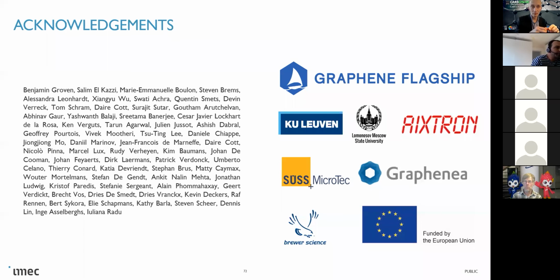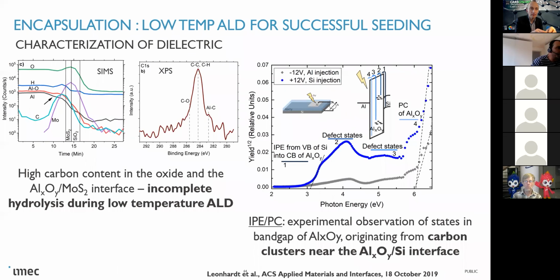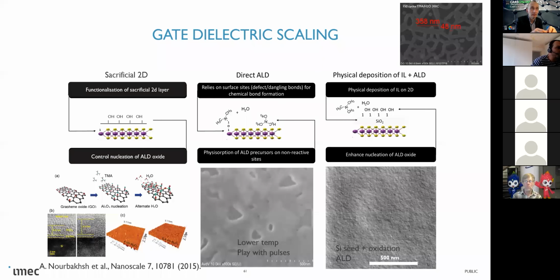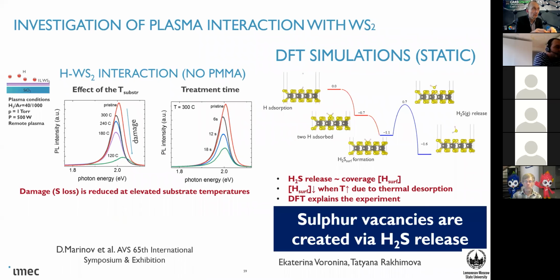Yeah, well, in the initial phase, we were not really understanding our results, and then we had to go to ab initio modeling to go deeper into the results. And well, it should be as gentle as possible, but still you need to have a relatively higher temperature, because the temperature prevents too much hydrogen from sticking to the 2D material. But it should be very gentle, because otherwise you etch. And the etching of the polymer residue is extremely fast.